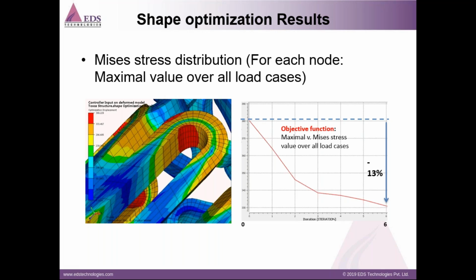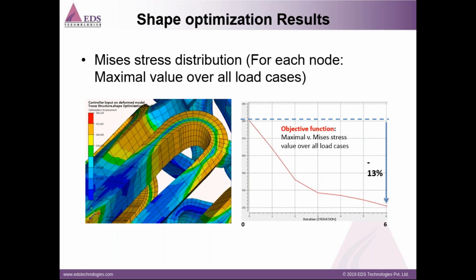On the right-hand side, you can get a slightly better understanding of the curve, how the maximum stresses are changing over multiple iterations. It all starts from a maximum stress of 380 MPa, mainly in that U-shaped region, and you can see the same in red in the contour plot. Over 5 or 6 iterations, the stress has been reduced from 380 to 330 MPa, which is nearly a 13% reduction in the maximum von Mises stresses.